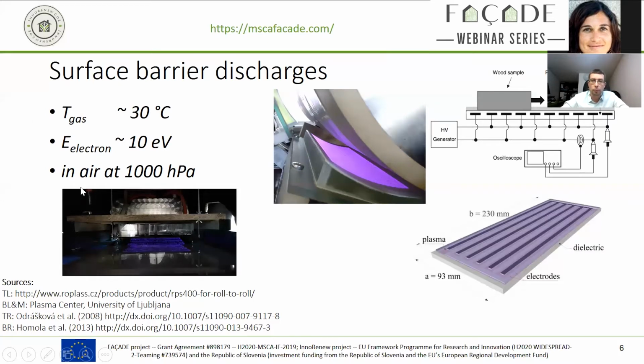There's a different way to set this up that's then independent of the thickness of the sample, and these are so-called surface barrier discharges, where the plasma is ignited on top of a dielectric surface. So here's a schematic provided for this, where the electrodes are all embedded within an isolator, and the plasma ignites just on top of the plates. This can be in different kinds of shapes and forms. Here on the left-hand side, there's one example out of our lab.